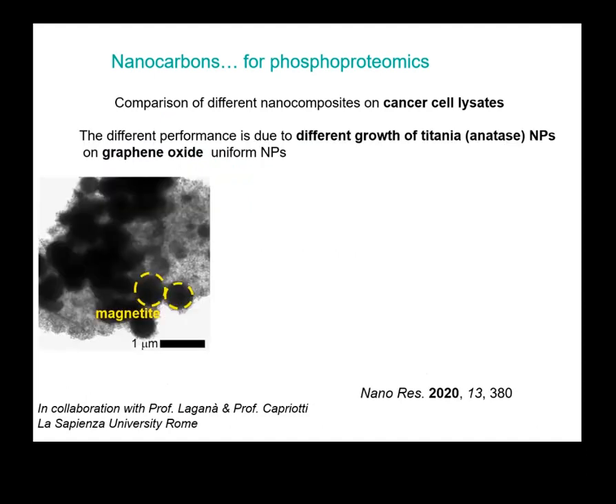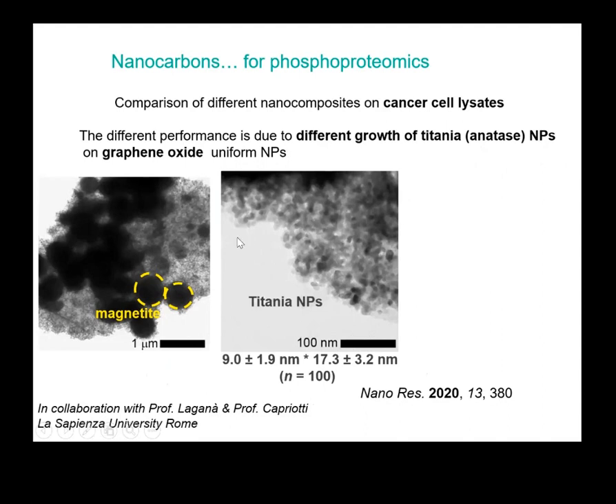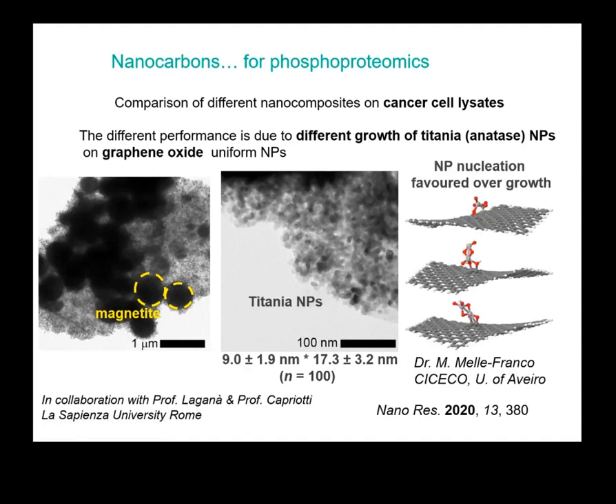And we looked more in detail at this composite, and here you can see in the TEM image a graphene oxide flake, and then the magnetite nanoparticles, these round nanoparticles that appear darker. And then you can see all these little spots, and through a higher magnification, it is possible to see that those are all titania nanocrystals. And in particular, also through a combination of experimental and in silico studies, thanks to the help of Manuel Melle Franco at CICECO, the University of Aveiro. And this collaboration was enabled by COST, actually. So it started with an STSM. Manuel really modeled the materials and could provide fine details to see how the nucleation and growth of titania was favored on both sides of the graphene oxide, where he modeled different types of oxidized functional groups, such as carboxylic acids, epoxides, and so on.